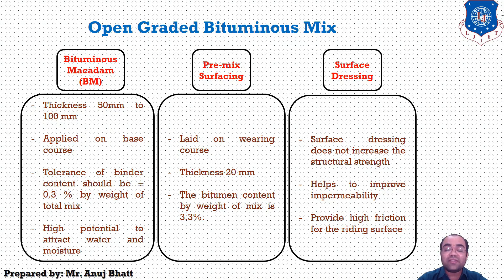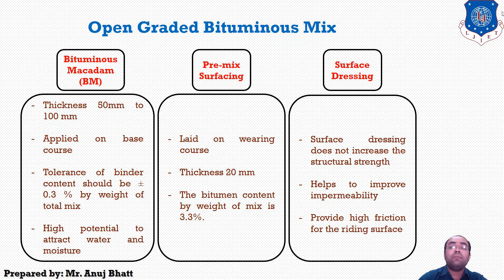The difference in temperature between the binder and aggregate shall at no time exceed 14 degrees Celsius. Mixing shall be thorough to ensure that a homogeneous mix is obtained in which all particles of the aggregate are coated uniformly. The mix shall be transported from the mixer to the point of use in suitable vehicles. Based on the aggregate application rate specified in IRC 14, as per the recommended practice for open graded premix carpet, the bitumen content by weight of mix should be 3.3 percent.